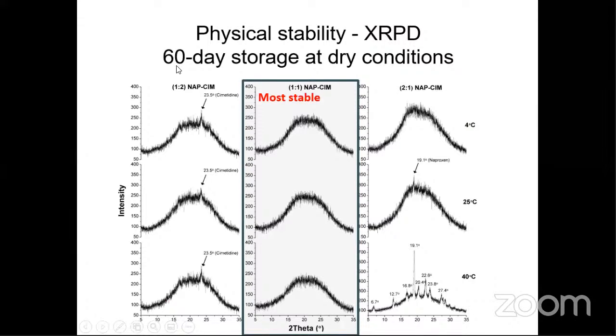We went ahead with a physical stability study: after preparing the amorphous material, we stored it at a dry condition for 2 months, then checked with XRPD. We can see that the 1:2 molar ratio already shows recrystallization peaks here, and 2:1 is the same - very obvious recrystallization peaks.